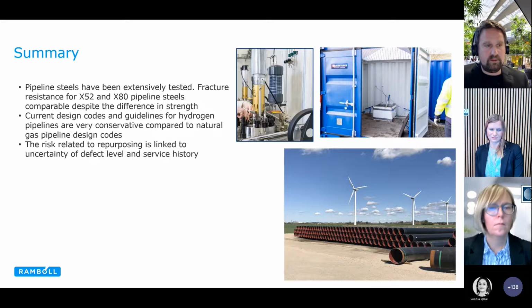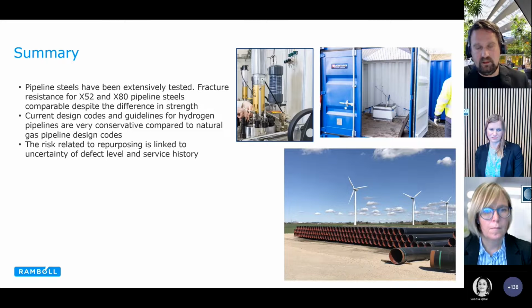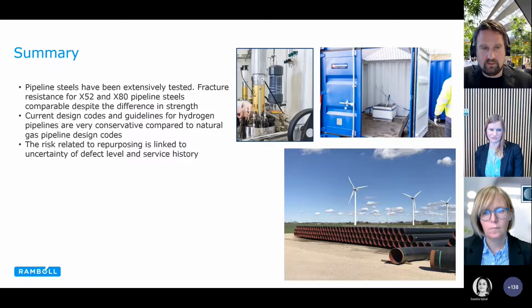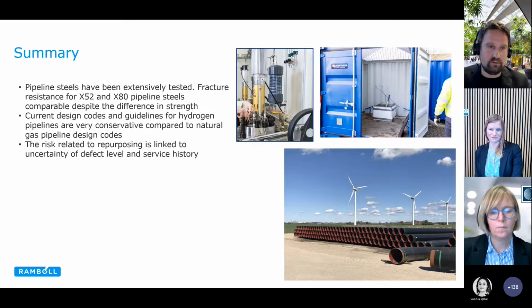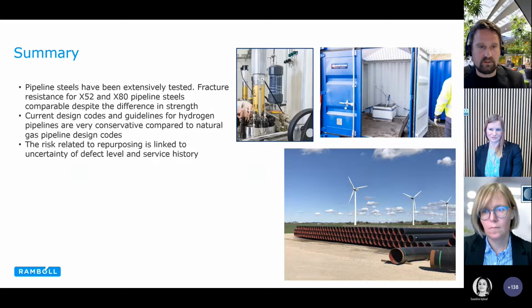What specifically Ditte was mentioning is that the defect level in the service history may be the most important parameters in terms of repurposing pipelines, since there are at least indications that the pipeline structure itself, per its welding qualification and per its pipeline steel applicability to hydrogen, seems promising, the testing of these. Then the unknowns would be, for specifically very old pipelines, the defects and the service history. But again, here also we have promising data for vintage steel.